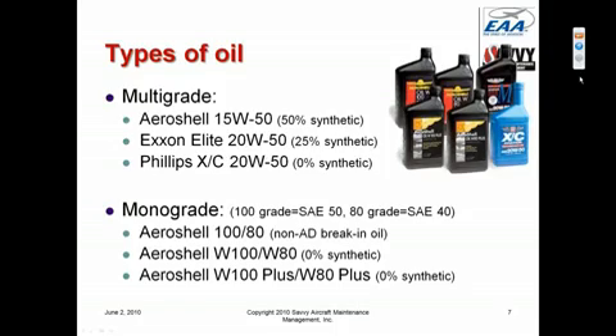Aeroshell W100 and W80 are petroleum-based monograde oils with minimum additive components in them. Aeroshell W100 is what I use in my own airplane and what I recommend for quite a few of my clients. Aeroshell W100 Plus and W80 Plus, which are again the 50 and 40 weight versions of the oil, are the same as W100 or W80, but they have some additional additives, including an anti-scuff additive called triphenyl phosphate and an anti-corrosion additive.